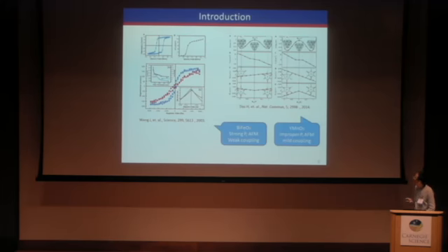First, we know that bismuth ferrite is well known as the first room-temperature multiferroic. It has a very strong polarization due to the large displacement of the A-site bismuth and also its lone pair. And the G-type antiferromagnetism originates from the B-site iron. There is a relatively weak coupling between the two quantities because they are from different sublattices.